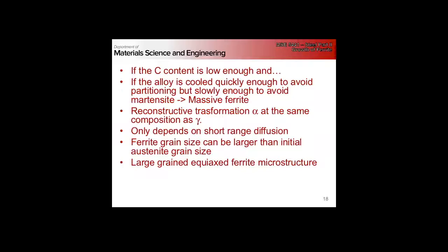But thanks for that introduction into massive ferrite. So if our carbon content is low enough, and if we can cool our alloy quickly enough to avoid partitioning, but slowly enough to avoid martensite, we can get a massive transformation. That's reconstructive, a diffusion-mediated transformation where our ferrite is the same composition as our austenite. And that's only going to depend on short-range diffusion because everything is the same composition - we're not partitioning carbon out from our ferrite, we don't have this diffusion field out in front. So it's only atomic jumps across the growing interface - it's interface controlled.